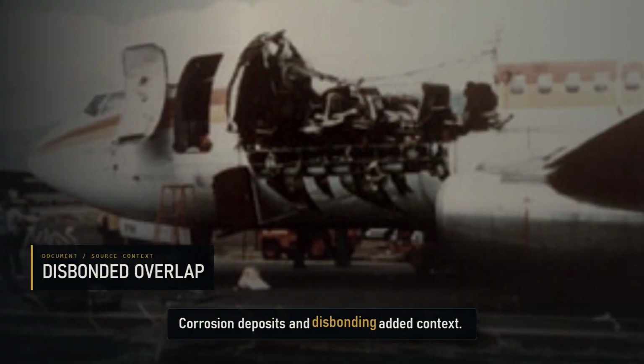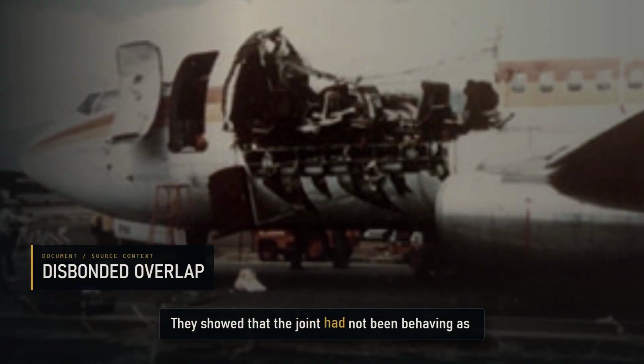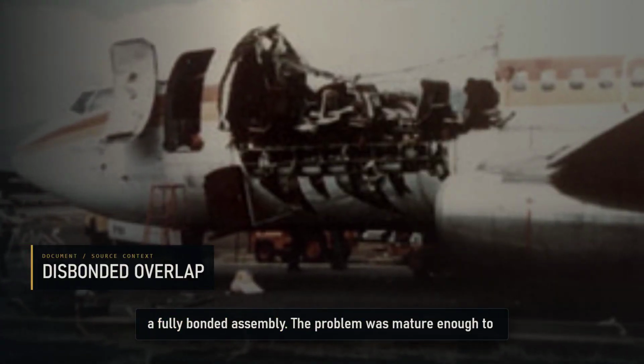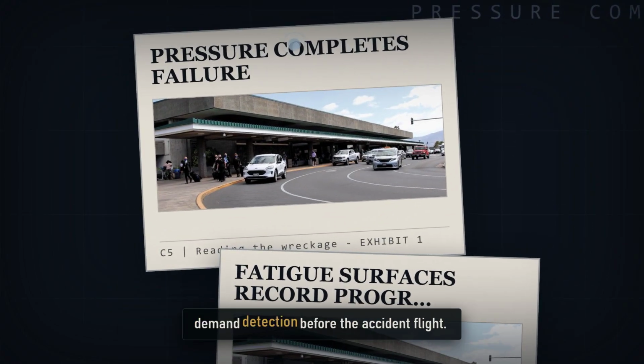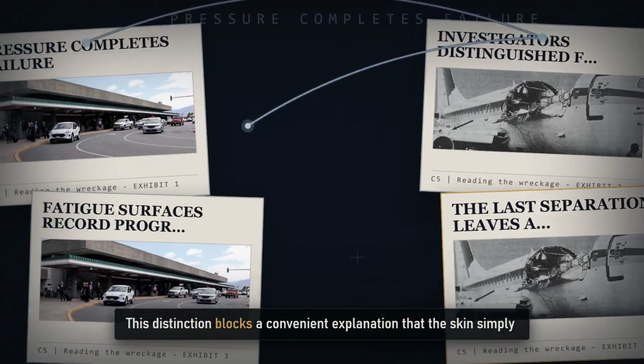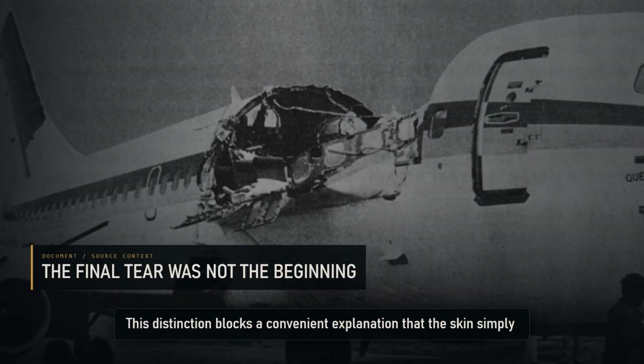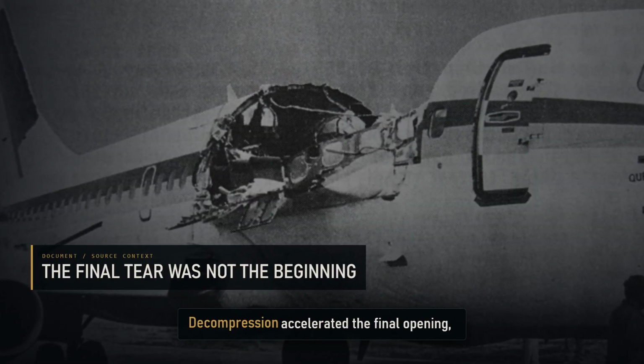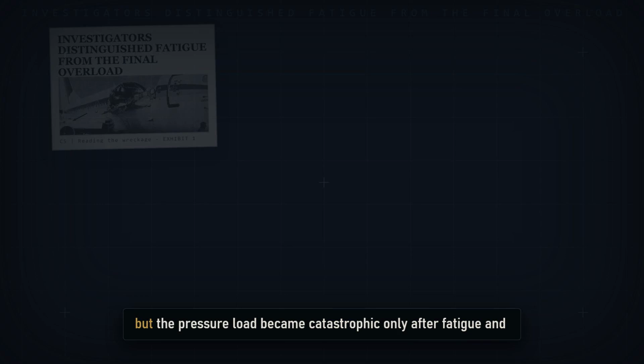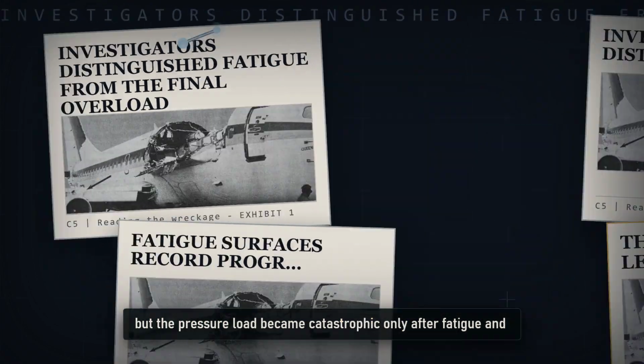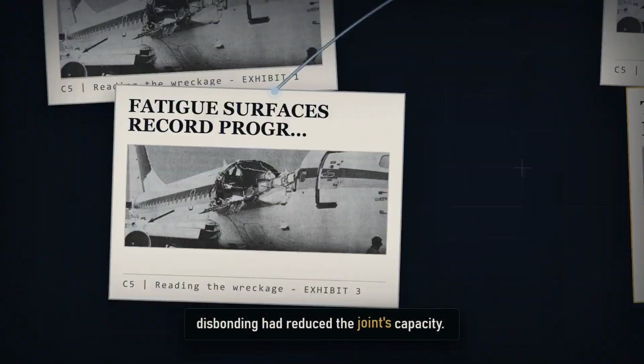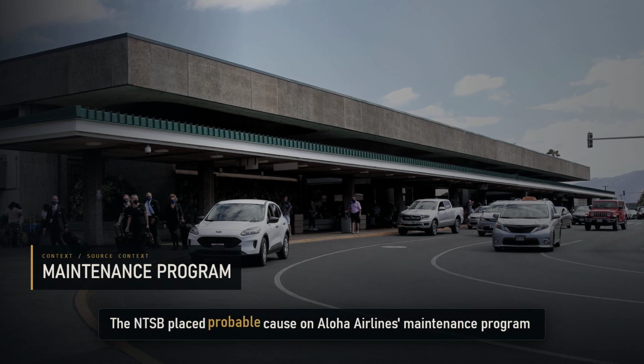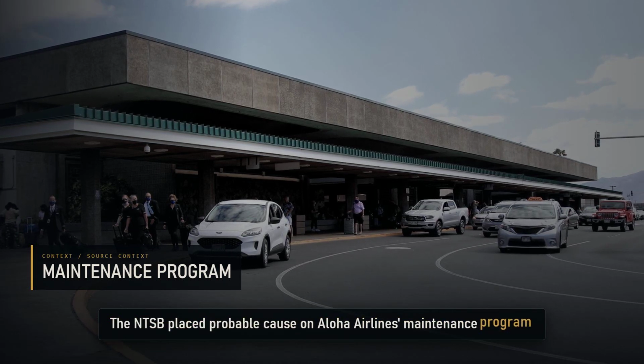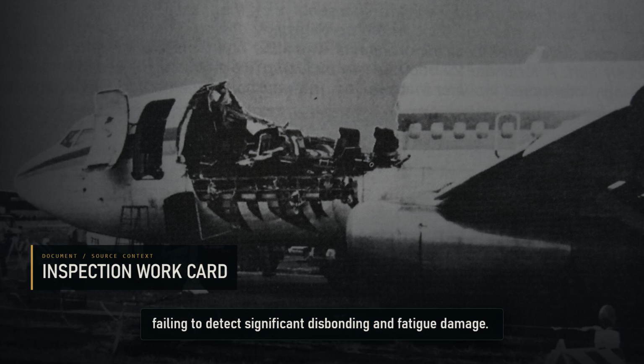Corrosion deposits and disbonding added context. They showed that the joint had not been behaving as a fully bonded assembly. The problem was mature enough to demand detection before the accident flight. This distinction blocks a convenient explanation that the skin simply tore because decompression was violent. Decompression accelerated the final opening, but the pressure load became catastrophic only after fatigue and disbonding had reduced the joint's capacity. The NTSB placed probable cause on Aloha Airlines maintenance program failing to detect significant disbonding and fatigue damage.